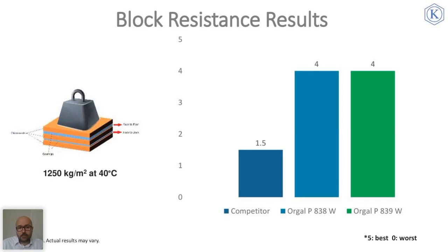In this test, competitor binder was remarkably worse in the block resistance performance from 0 to 5 scale. It gave a performance between 1 and 2. Our reference binder, Orgal P838W, together with new development, Orgal P839W, outperformed the competitor binder, and they both gave almost perfect block resistance results.